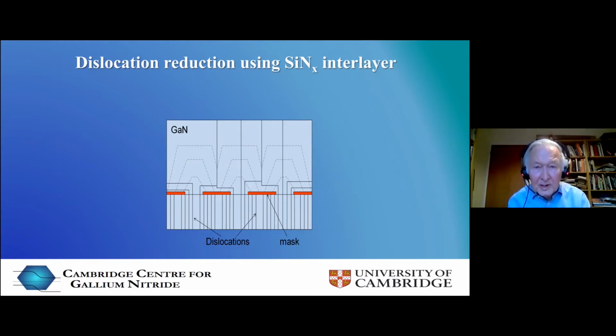But on the other hand, dislocations still go through these random holes, and we can reduce that dislocation density further, because when we're growing the bottom layers of gallium nitride, we do layer by layer growth. When we grow the gallium nitride on top of the silicon nitride, we change the growth conditions and we do island growth. And dislocations which come up through the holes may hit a side facet of one of these islands and go right, as it were, and another dislocation coming up through an adjacent hole may hit another side facet and go left, as it were, and these two dislocations can meet and annihilate, or they disappear then, or the two dislocations can be one dislocation, and that reduces the dislocation density.